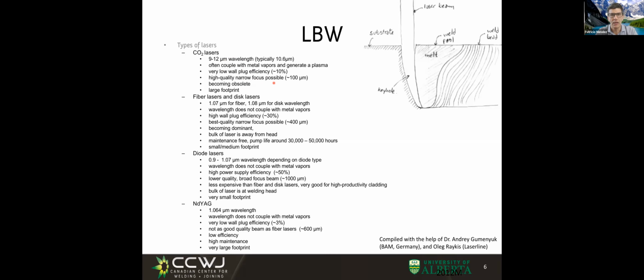There's another thing. At that long wavelength, this metal vapor that is generated, for example, in the keyhole, is somewhat opaque to the laser beam. So the laser starts to heat up the vapors. And when it heats up the vapors, guess what happens? We have a plasma. Not because we have an electric current, in this case, but we have a plasma. And this plasma acts as a shield to the light. So the plasma starts to absorb the light, but the metal doesn't absorb the light. So the efficiency of CO2 lasers is very low. It's an old technology. Some companies start just to take their CO2 lasers out and get some of the modern lasers. Just in electricity, they recoup the money.